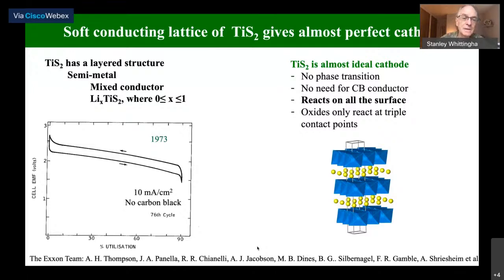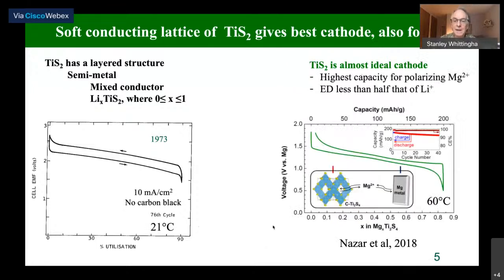TiS2 is still of great interest. Linda Nazar, Waterloo University in Canada, used it as a cathode for magnesium cells, and her magnesium cells now hold the record for the highest capacity for a magnesium cell and also the best recyclability. So you can see this is her discharge and charge curves. This is for, in fact, the spinel version of TiS2, not the layered version, but the layered version is very similar.